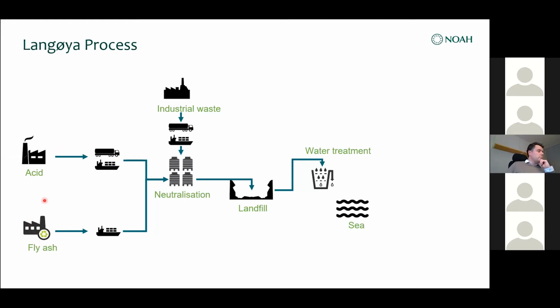The other big waste stream is fly ash. We receive approximately 300,000 tons of fly ash each year. And the alkaline to acid ratio here is almost in balance. The fly ash is slurried with water and pumped into our neutralization plant, where we mix it with our sulfuric acid. And out of it, you get precipitation of gypsum.